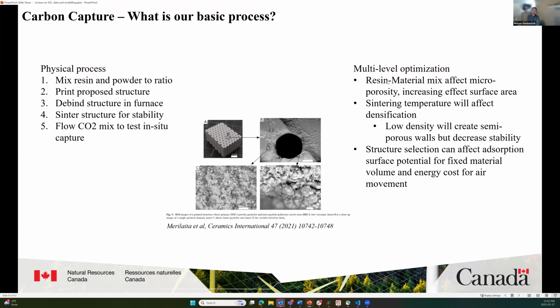So that's when we realized that in the burn off and sintering process, the temperature and time that we sinter, and the amount of resin material mix we choose in the first place, will affect the densification. And while the nanopores are on the order of nanometers, there are also going to be micropores on the order of the zeolite particle size, which gas can do some surface penetration. So there's some optimization that we will potentially do there, which we're not presently simulating in the CFD.